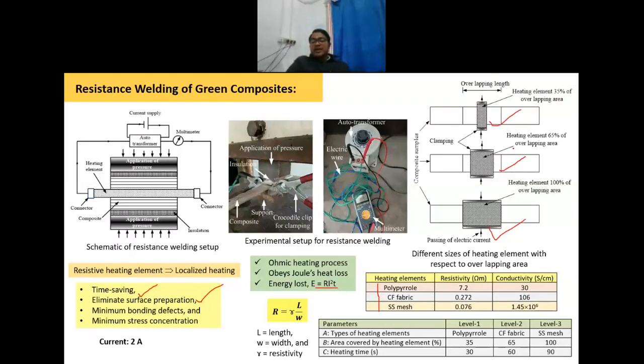This heating element is a different material, and it becomes an integral part of the joint, because we cannot remove it once we perform the joining operation. It becomes an integral part of the specimen. So we wanted to investigate whether we need to cover the whole overlapping area with the heating element. What we observed is that even if you don't cover the whole overlapping area, we still get the required joining strength.